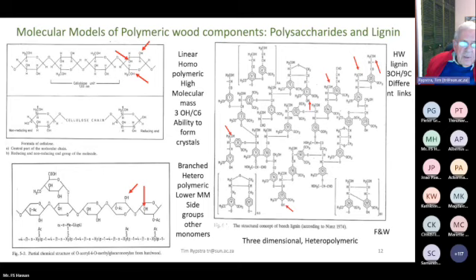Going to the other polysaccharides, there are also hydroxyl groups. I only indicated the 2, and the other main chemical component, which is in this case a hardwood lignin. It's got 3 hydroxyl groups for every 9 carbon rest. Now this is a typical 9 carbon rest with a ring structure with a side chain. And lignin is 3-dimensional, heteropolymeric, in other words, it has different building units, and the same with the hemicelluloses. They also have different building units. Okay, the next slide.